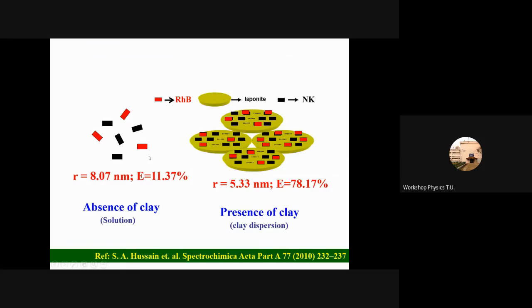Schematically, here I have shown that in the first case, in homogeneous solution, the molecules are randomly moving, the distance is higher, so efficiency is also less. But when the molecules are adsorbed on the clay surface, they are attached with the clay system and the distance becomes lower. Accordingly, efficiency, you can see, becomes 78.17%.